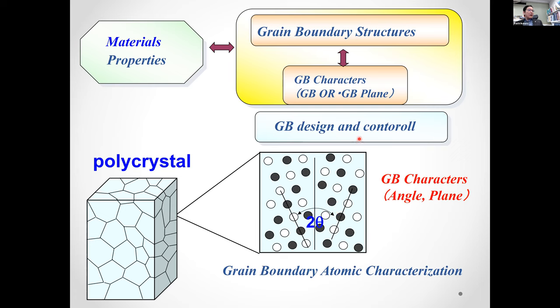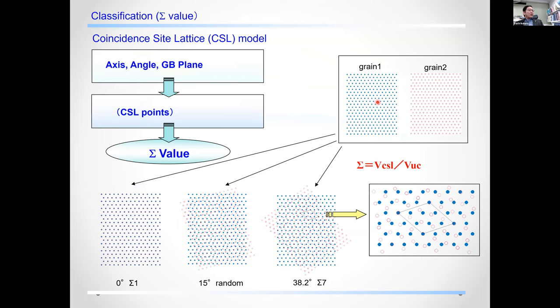Therefore, in order to understand the effect of grain boundary structures on material properties, we need to consider the grain boundary character. Then we use the same grain boundary characters to compare the structure and the properties. That is an important point. I will briefly introduce CSL. What is CSL? Coincidence site lattice models.